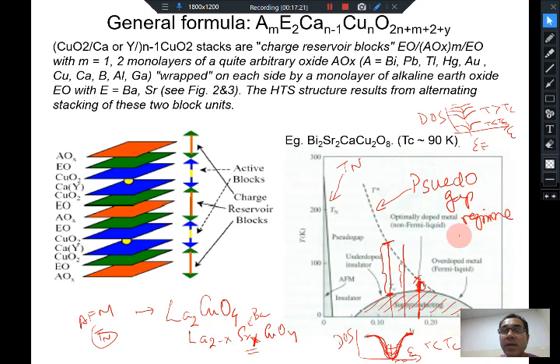regime. Namely, even at T greater than Tc, well above the superconducting transition temperature, there is evidence of some sort of pairing, some sort of gap in the single particle density of states, which survives up to well above Tc. And here it is thought that there are fluctuating Cooper pairs, like superconducting puddles, if I may say, microscopic superconducting puddles which are present inside the system, but these puddles are not phase coherent.